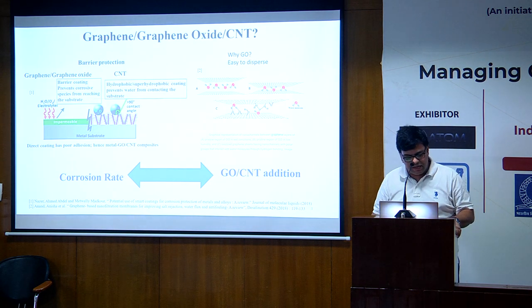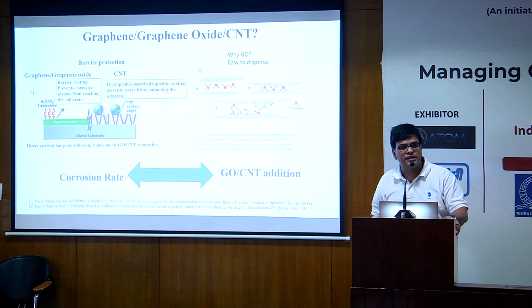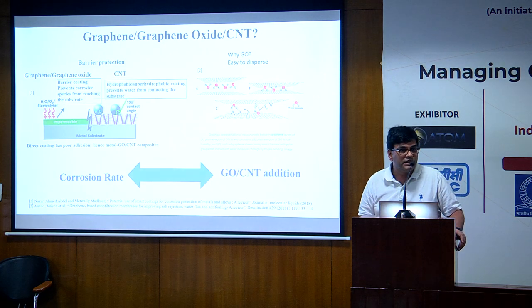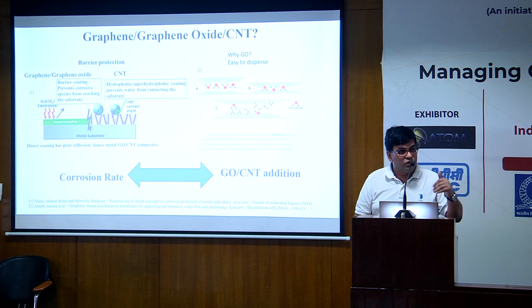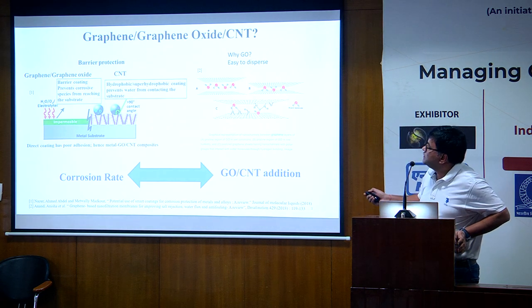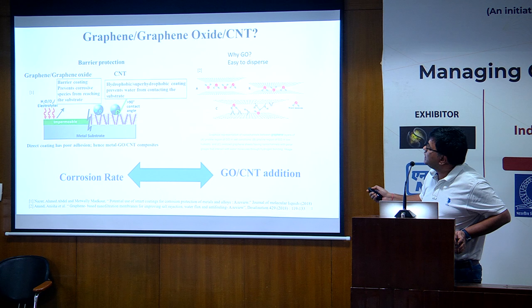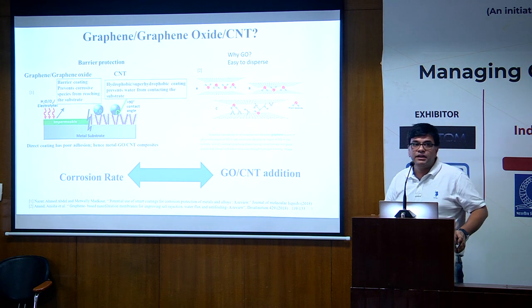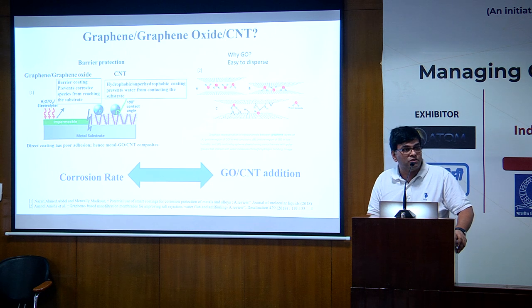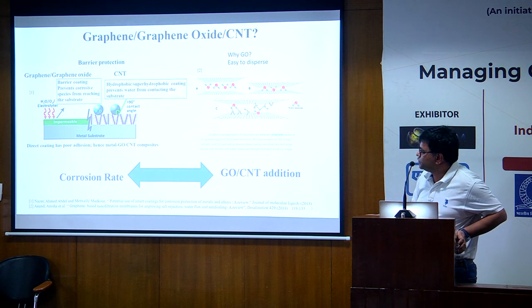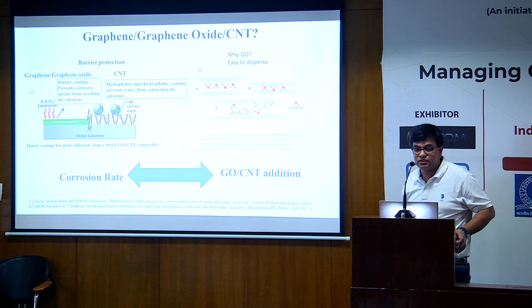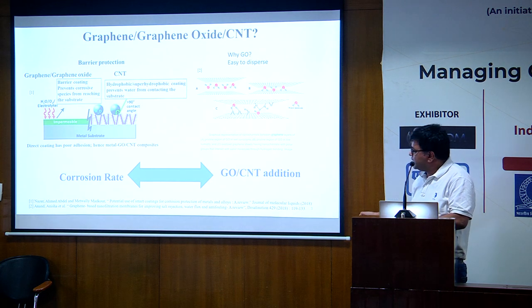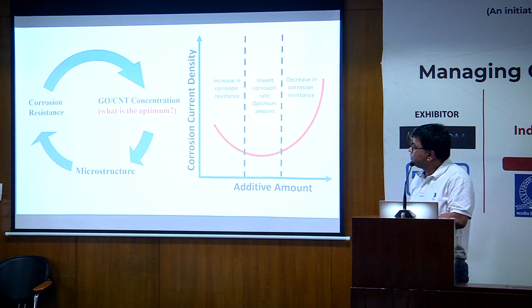It is an area which has now attracted certain attention because graphene is impermeable and it can stop the seepage of the corrosive media within the body of the coating, and carbon nanotube is hydrophobic and therefore it can repel water and in some way help in reducing the extent of aqueous corrosion, right? The corrosion rate people have studied is connected to the amount of additions of CNT and graphene oxide. This GO is graphene oxide.